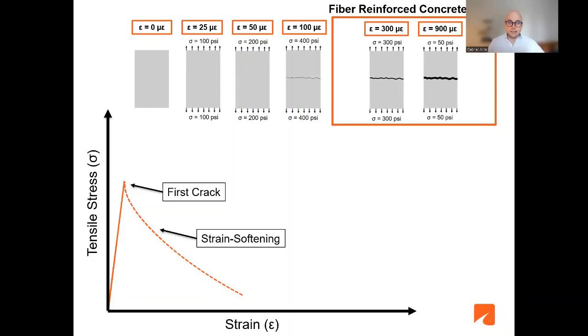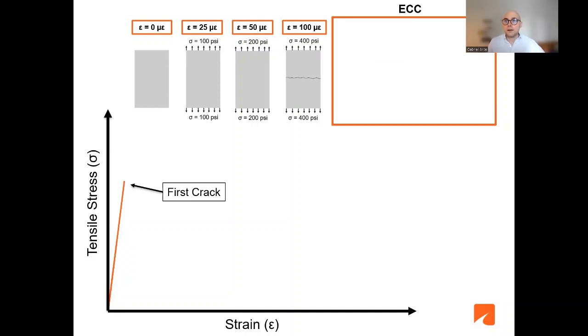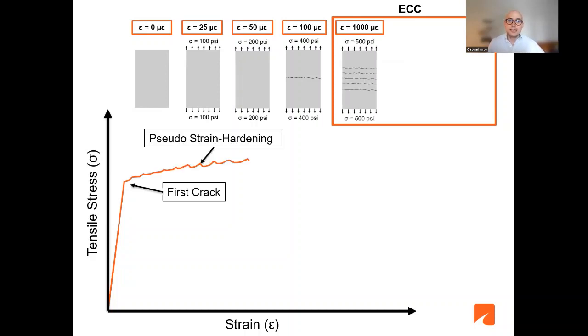That's why I have this as a plot with a dashed line. Now, interestingly, the ECC, engineered cementitious composite, behaves rather differently. So how does the ECC behave? After that first crack, you continue deforming the material, and you actually have a phenomenon called pseudo-strain hardening, meaning your material can hold more load after the crack.